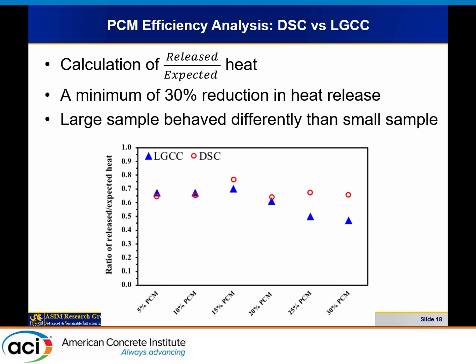So we wanted to see the differences between DSC and LGCC in the smaller sample and the large sample, and see what would be the difference that we get. So we did some extra calculation, and we normalized the amount of heat release. This is the released heat calculated through LGCC or DSC divided by the expected. As I mentioned earlier, we know how much PCM we put in, right? So we could have an idea of the amount of energy, the thermal reservoirs that we put inside, and how much of that is effective.